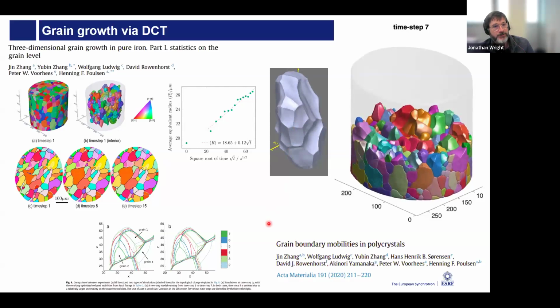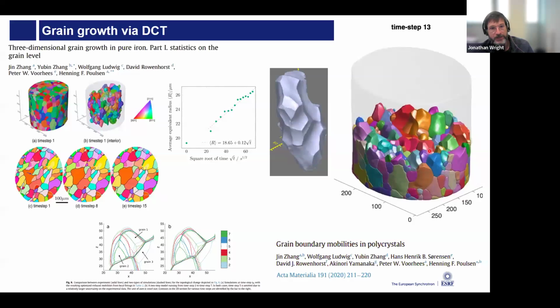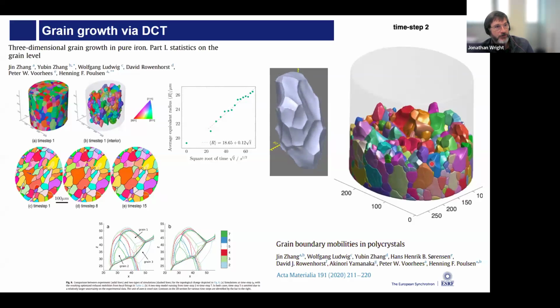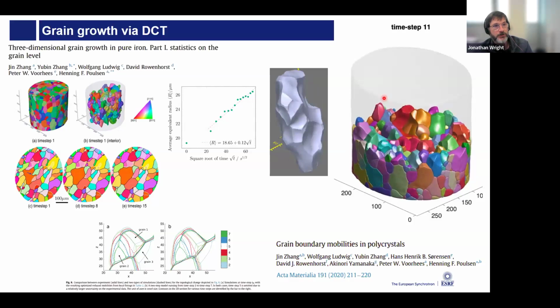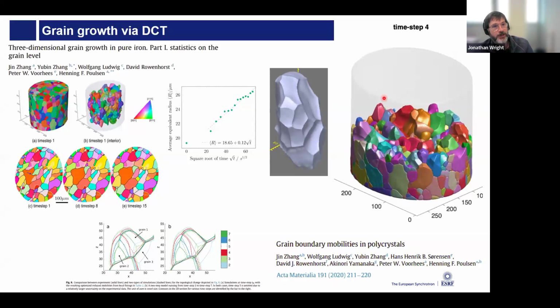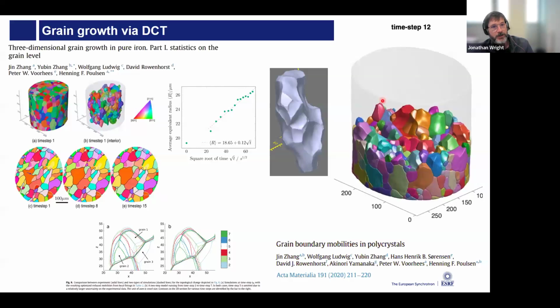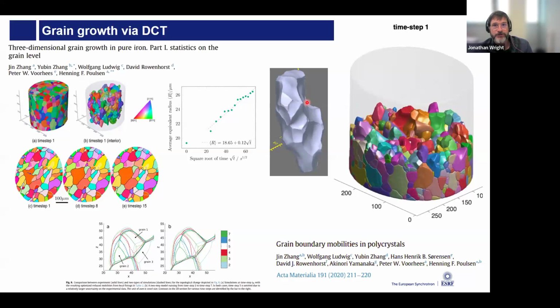And there's then some very detailed analysis because you have more than, I think, 13,000 grains. You have many, many different grain boundaries. And the question is which grain boundaries are moving in which directions and why? And something I look forward to seeing in the future is to do these kinds of experiments continuously as in situ experiments without having to interrupt. In this case, when the data were collected, we had to stop the experiment, interrupt, and then measure. And I think it would be wonderful to do this experiment as a continuous movie in 4D in the future.